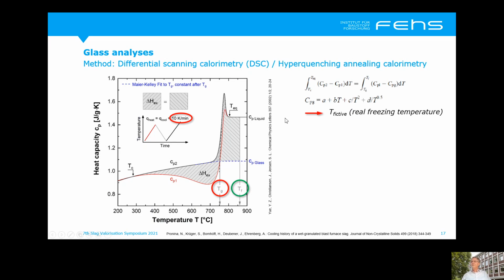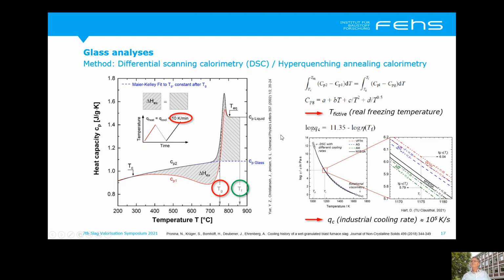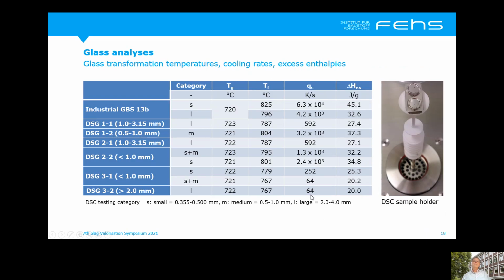If you have the so-called fictive temperature, so the real freezing temperature, and if you know the viscosity at this temperature, you are able to calculate the cooling rate Q. The cooling rate is normally in the range between 1,000 and 10,000 Kelvin per second, very fast. The results of the glass analysis, which were done by our colleagues from the Technical University of Clausthal, you can see here. It is important to say that we measured unground particles of different sizes. We used small, medium, and large particles, and therefore we have to differentiate between the different particles and to compare only particles of the same fraction.